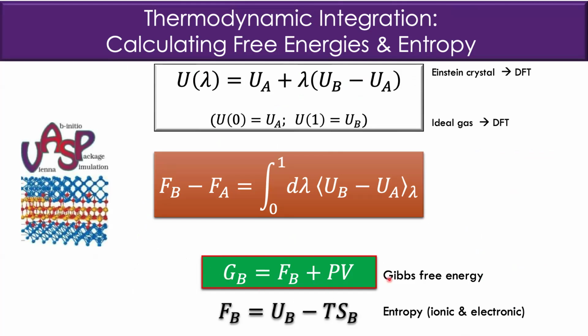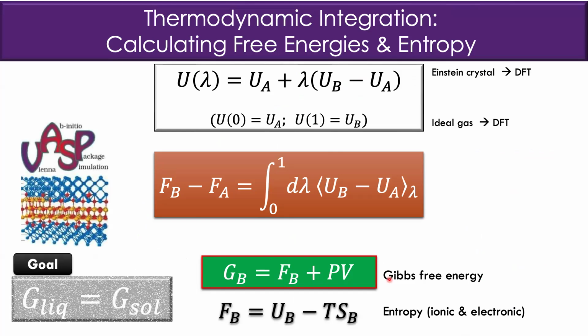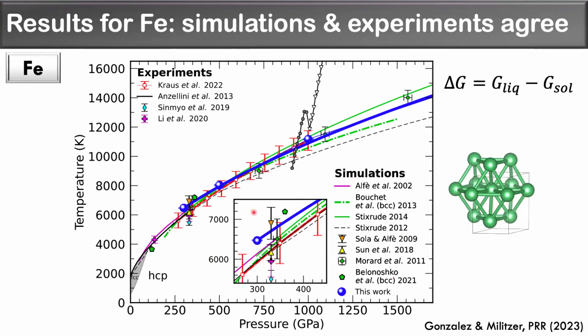But the main quantity we're after is the Gibbs free energy. What is the Gibbs free energy of solid iron and of liquid iron at different pressures and temperatures? And all we want to investigate here is where are the conditions where the Gibbs free energy of the liquid is the same as the Gibbs free energy of the solid, because that's the definition in thermodynamics of the melting point, right? So we ran a series of calculations and we verified where these two energies meet, and that's how I obtained these blue marbles that you can see here, which are all melting points that together make a melting line. So the first thing that you can see here is that it agrees very nicely with the experiments that I showed you at the beginning, with the error bars in red, right?